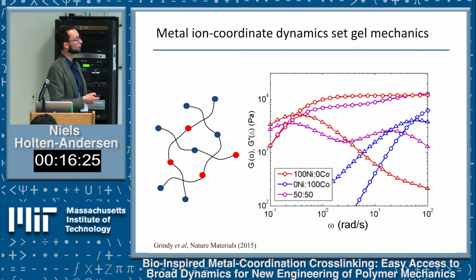What you see with the nickel network, the pure nickel network, is again a slow, almost elastic-like material. For the cobalt network, it's a much more fluid-like material. The crossover is at a much higher frequency.